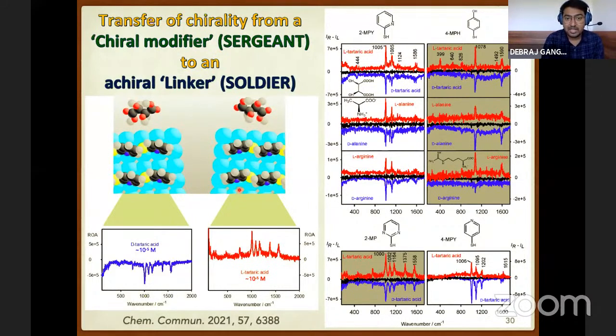or a soldier. So we have used different achiral linker molecules, which are 2-mercaptopyridine, 4-mercaptophenol, 2-mercaptopyrimidine, 4-mercaptopyridine. These achiral molecules we have used as linkers. Now, why have we selected these achiral molecules particularly? Because these achiral molecules are known to have very strong surface enhancement properties. All these have the thiol group, and they can produce excellent enhancement in surface enhanced Raman spectra. So we have tried to modify these achiral molecules and induce chirality in them by using a chiral modifier.